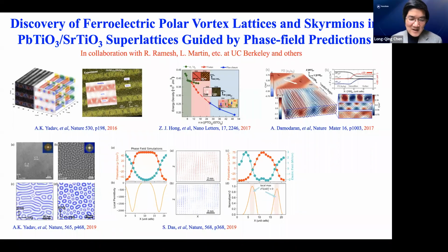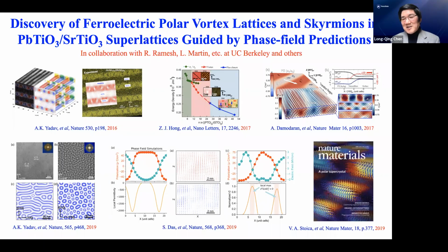That's really related to the second derivative of energy with respect to, in this case, polarization. And if you hit states like the mixed twin and vortex states, you can produce even fascinating, what we call supercrystals.